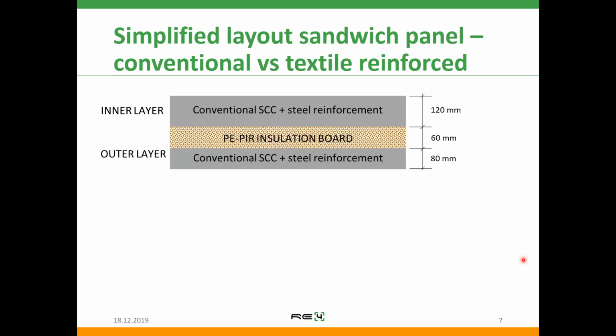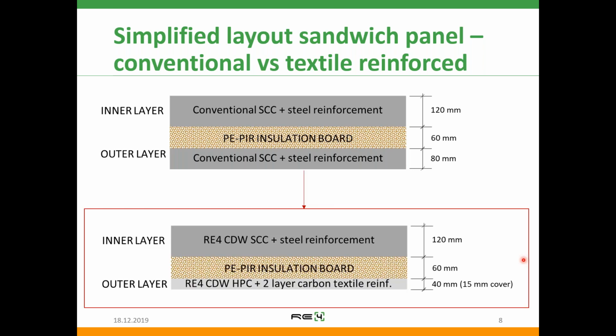So, a rough layout of a conventional panel. This is how it looks, a little bit simplified, with inner and outer layer surrounding the insulation, and having a conventional self-compacting concrete, which is steel reinforced, just like Ruben showed in these nice photos from the CREAG factory. But what we have done for this non-structural panel is, like I said, used CDW-based self-compacting concrete, and instead of an 80 millimeter thick conventional concrete layer, we have reduced the thickness by half and instead use high performance concrete and carbon textile reinforcement, which is actually one layer. Sorry for that, it's wrong in this image.